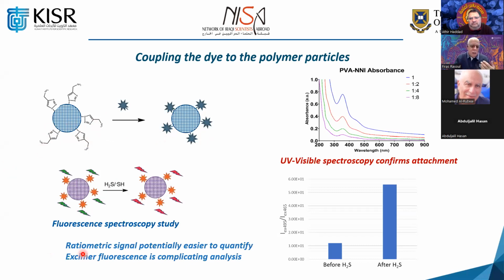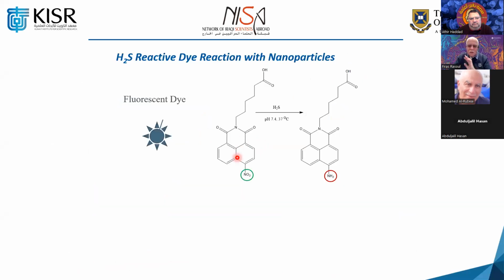So we found probably a ratiometric signal potentially easier to quantify, compared to looking into the excimer fluorescence, which is very, very difficult and very complicated to analyze. So we found this, even though there is some background fluorescence coming up before exposure, after exposure to H2S you find the peak is really extremely high. So there is a good fluorescence coming from that. This type of work, definitely this project and this approach, requires some fine tuning. And I think we're still having some difficulties in fine tuning all this work. So hopefully we will be able to do it in the very, very near future.